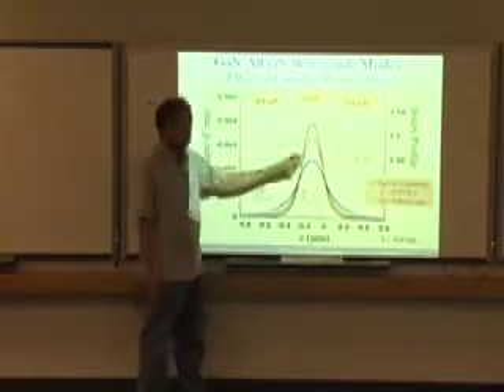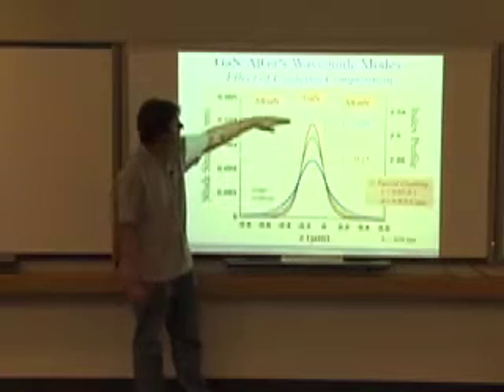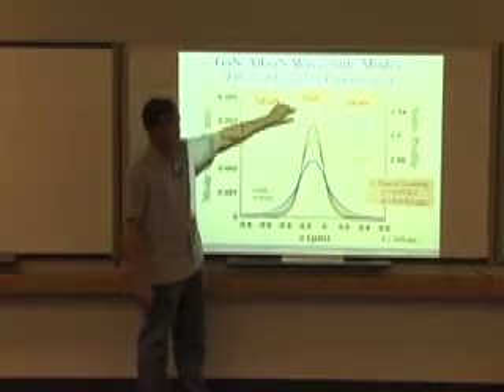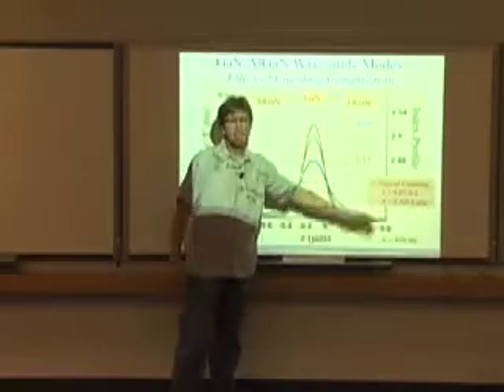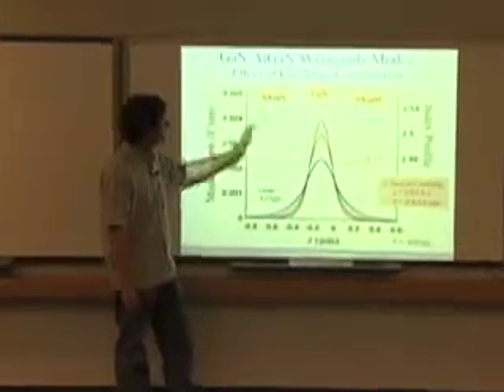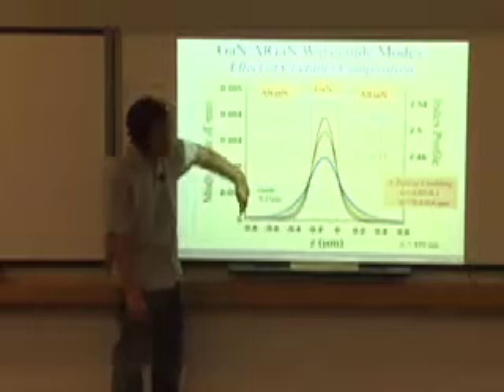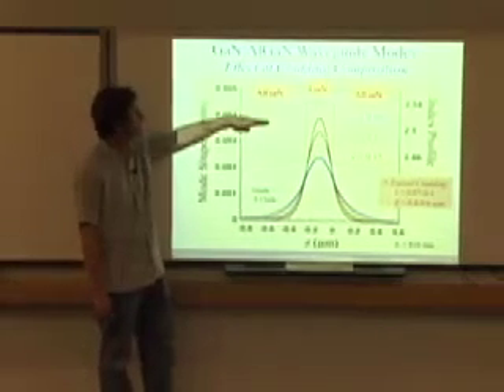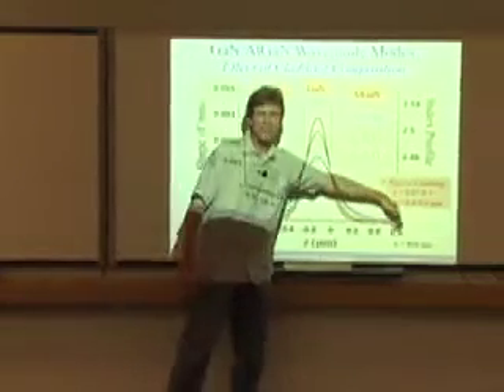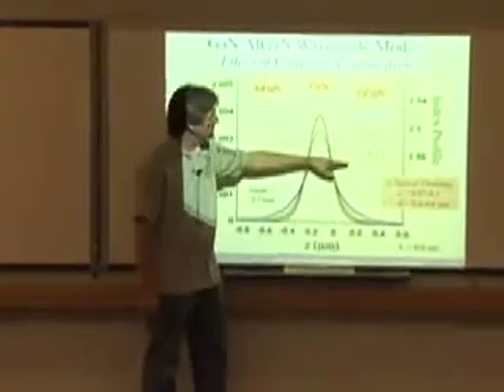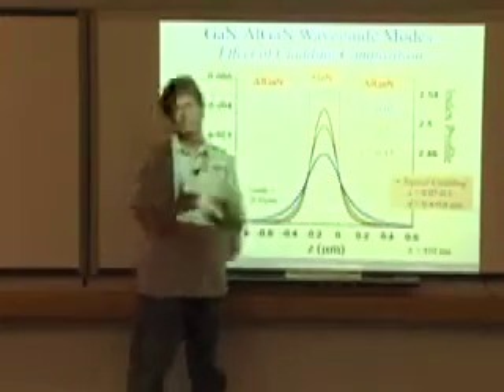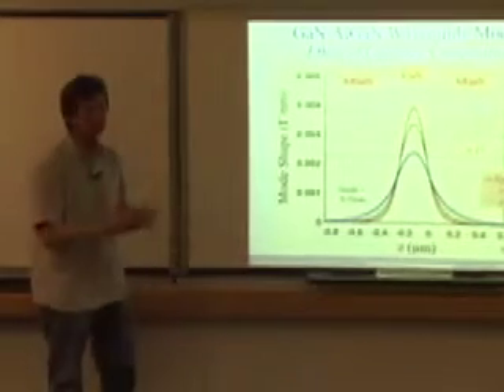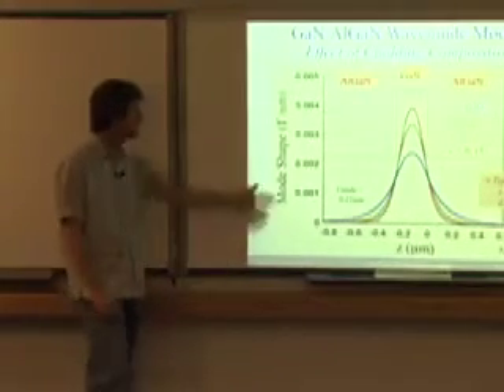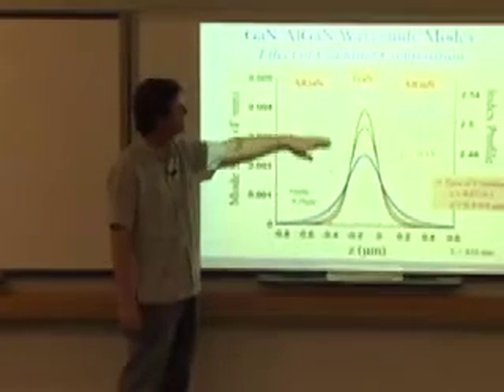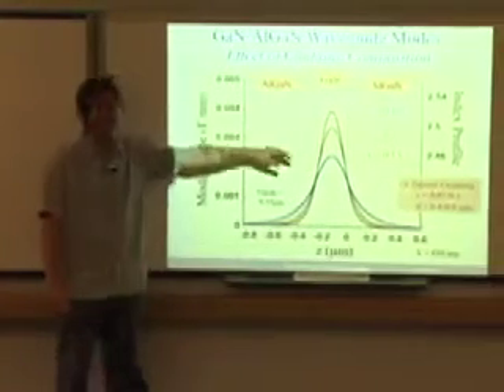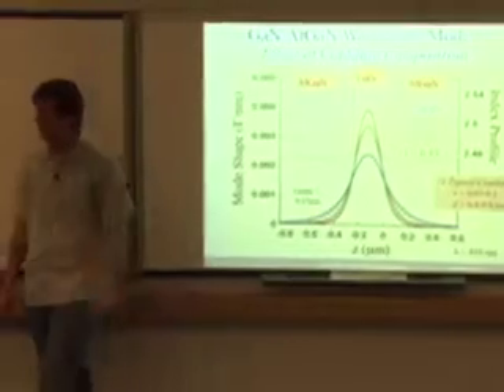You can live with 0.05, but there's a trade-off here, because the lower the aluminum mole fraction you have, the smaller the delta N, and the wider the mode will spread out. And when you grow these structures, you want to make sure that your AlGaN is thicker than that tail of the optical mode. So if you do choose to go with 0.05, you're going to have to go with more than a half micron of material. If you go with 0.15, you can get away with maybe 0.3 microns. And so there's a strain thickness trade-off there that has to be balanced. And so depending on the material quality that you're growing, your choice of cladding aluminum mole fraction was pretty key.